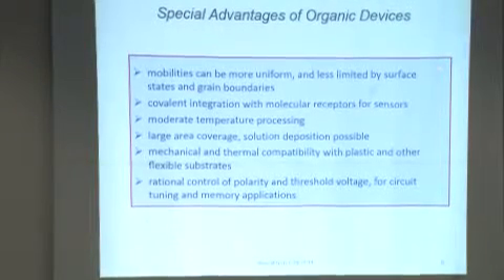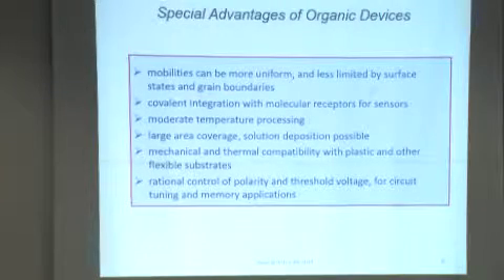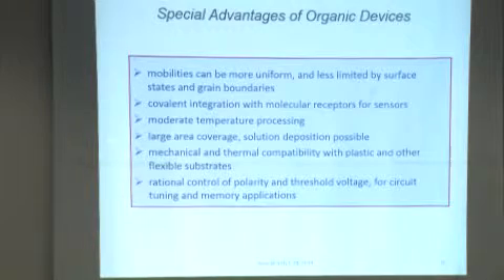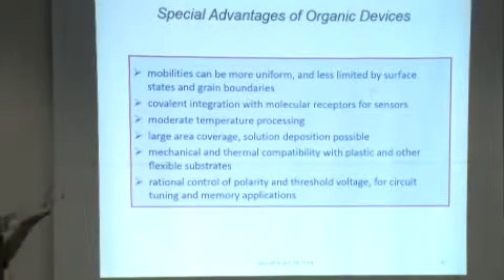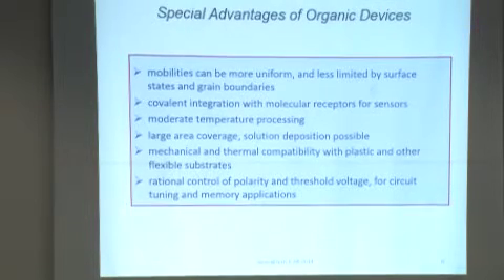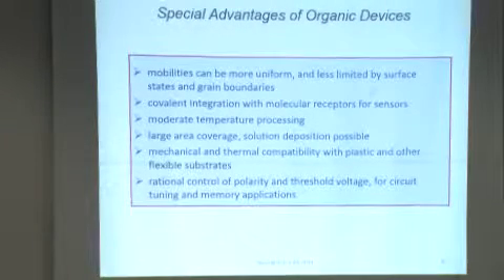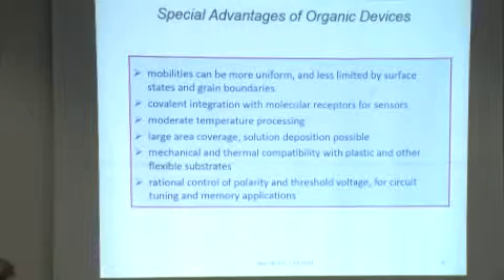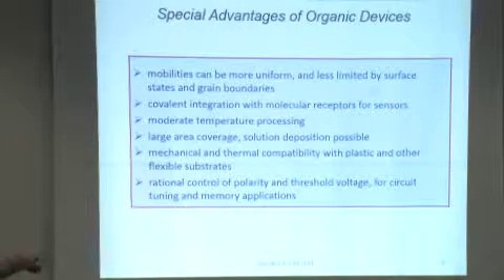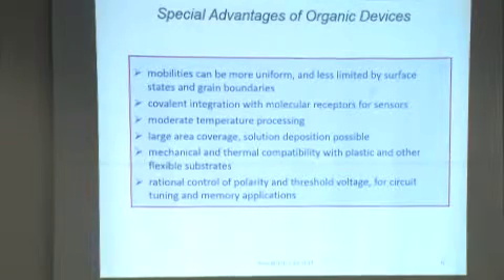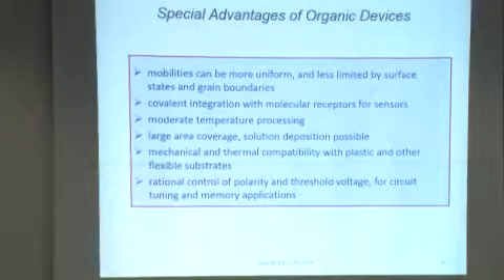I think I'm going to update this slide and delete the "less limited by surface states and grain boundaries." I think it's more of a different issue, but there's still certainly issues with organic materials. You may be able to covalently attach receptors for sensor applications. The processing temperatures are most likely going to be much more moderate, maybe low temperature processing. You can do solution deposition and cover a very large area. There's mechanical and thermal compatibility with plastic and other flexible type substrates.